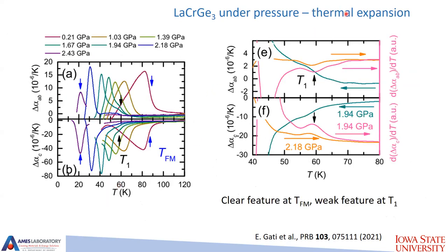You can do thermal expansion, and again, you see the ferromagnetic transition in both directions. Moreover, you can argue, judging by shape, that you are going from a second order phase transition to a first order phase transition. If you look at the pressures near the horizontal line, you can see T1, although the feature is rather weak, but you don't see T2.